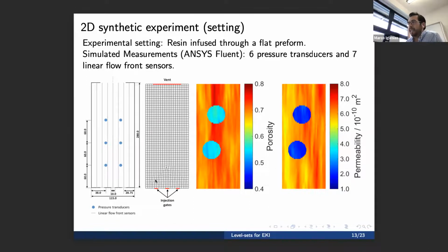So we have, again, this setting for composite manufacturing, where we have this domain. We have injection of the resin at the bottom, the injection gates; this is the computational domain that we use. These 6 dots that you see here are where we collect pressure, and these 7 lines are the places where we collect measurements of the front.